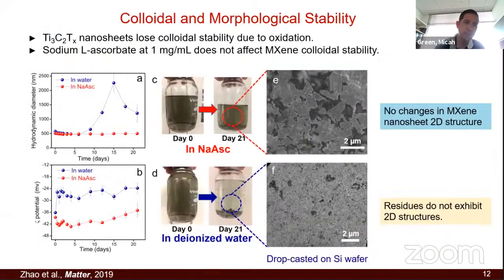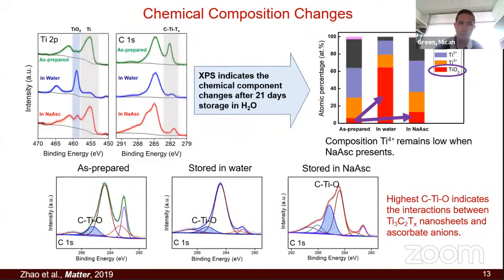You can also measure this using DLS. This is the hydrodynamic diameter. It's pretty stable if you use an antioxidant. In water, you start to get big aggregates, which you can actually see here in the SEM. Same thing, the zeta potential of these materials in water is fairly stable if you use an antioxidant, whereas things can start to change even on a short time scale if you don't, and eventually these things will crash out and you don't see any kind of 2D structure anymore. So this shows how powerful this technique can be.